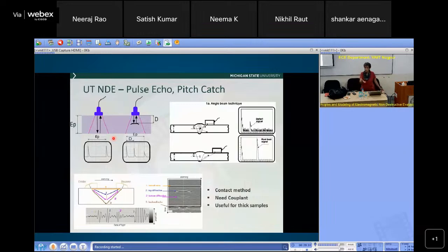So what I've talked about here is a contact method. Okay, that's another thing I should point out, which is not there in the slide. Another way of conducting an ultrasonic NDE is to immerse the whole thing in water, in a big tank, in which case the water becomes a coupling medium. I don't need to be in contact with the sample. I can just scan from 2 inches above the sample. But the whole sample has to be immersed. So that's called the immersion method for ultrasound. That's the contact method or the immersion method.